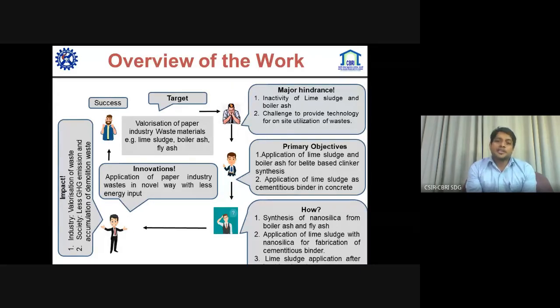The primary objectives associated with this are application of lime sludge and boiler ash for belite-based clinker synthesis, and application of lime sludge as cementitious binder in concrete. How can we do this? Synthesis of nanosilica from boiler ash and fly ash, because they are very silica-rich materials. And the second one is application of lime sludge with nanosilica for fabrication of cementitious binder, and lime sludge application after heat treatment. That will be low heat treatment, not at 750 to 850 degrees C.